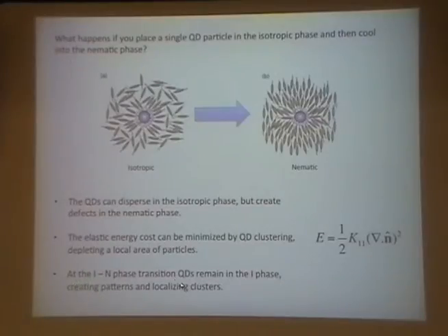So as we go through the phase transition, there's another effect that can also happen. So first of all, we have the clustering. Secondly, as you go through the phase transition, you're going to have domains of isotropic phase, which are gradually shrinking. We've also observed that the nanoparticles prefer to remain in those isotropic domains. So this can be more like a phase separation effect as well. Nanoparticles love to be in the isotropic phase. They hate the nematic phase. It's ones with this kind of surface anchoring. So they can be clustering, going to defects, and they also try to stay in the isotropic phase as long as possible. And I'll show some experimental results about that in a bit. So we found these are the two main interactions.